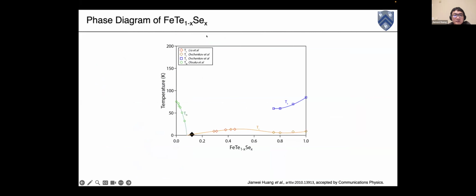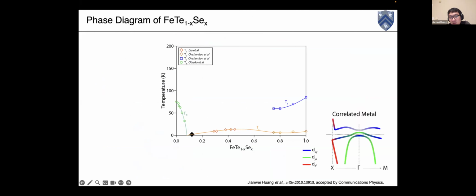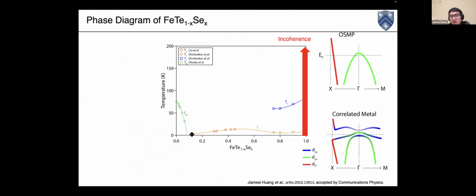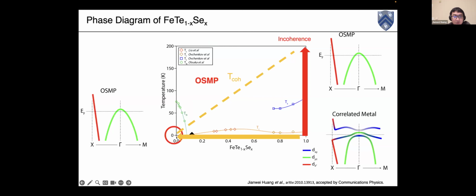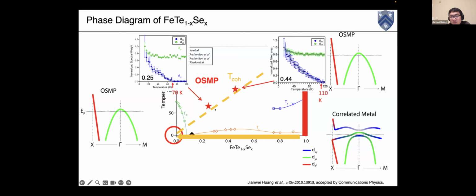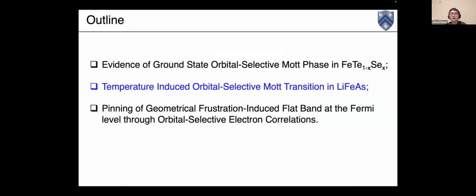So then I can summarize this part by this phase diagram. In this FeTeSe series, at the iron selenium end, we have a very correlated metal with increasing temperature. At high temperature, we will have a temperature-induced OSMP phase. And when we go from iron selenium to iron tellurium, we also evolve into an OSMP ground state. And then the coherence temperature from FeSe to FeTe will gradually decrease. This is also nicely captured by our temperature-dependent data on different compounds. Okay, this is the first part of my talk.